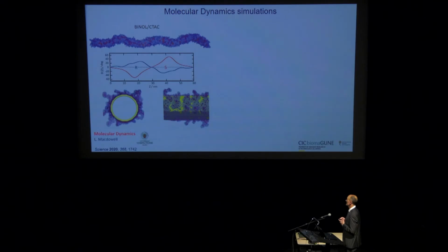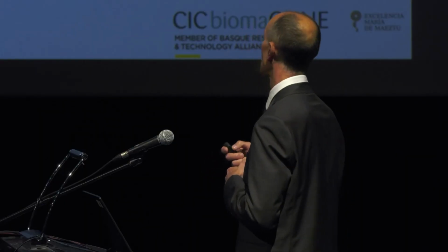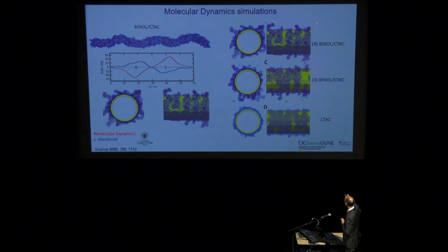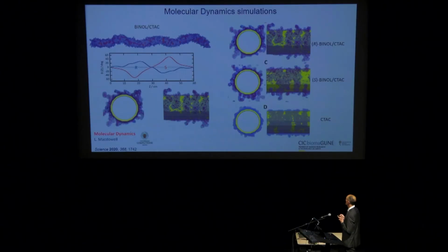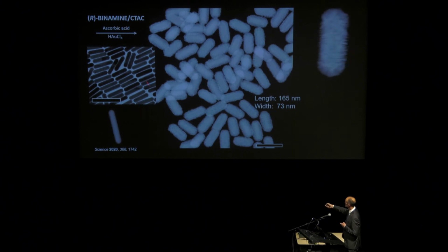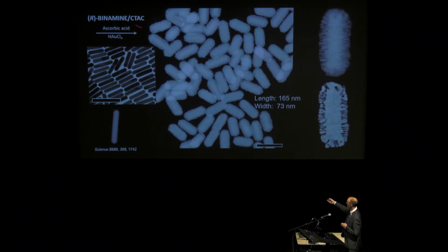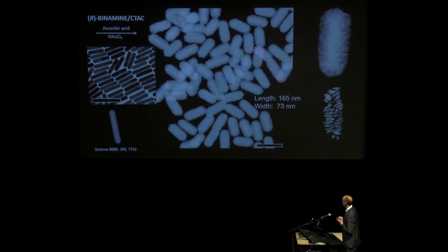And so we did again theoretical modeling by molecular dynamics. We found that there is a hint that the different enantiomers will lead to different organization of the micelles around the metal cylinders. And then we decided to run the experiments, and starting from nanorods like this, we were growing in the presence of binamine and CTAC. And as you can see, we obtain grooves. The helicity is not extremely clear here, but quite interesting.